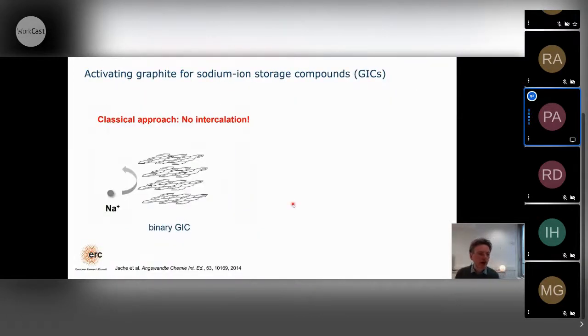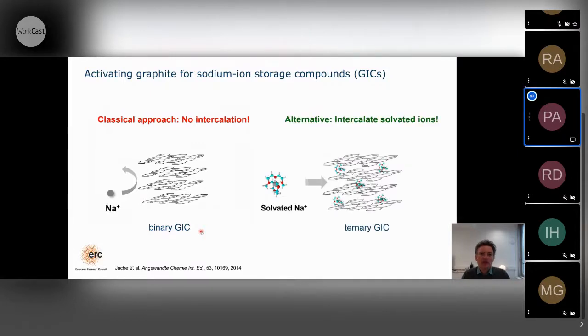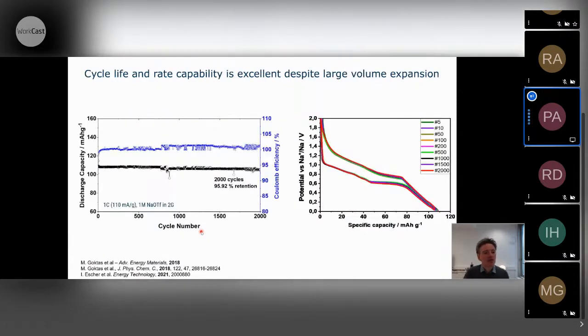From the classical perspective, sodium ions alone hardly intercalate into graphite. So there are no so-called binary graphite intercalation compounds that are rich in sodium. And what we do instead is intercalate solvated ions, so the solvation shell along with the sodium ion. In a lithium-ion battery, you really don't want this because it leads to fast aging. But in the case of sodium, this approach is quite promising because it's highly reversible. So we intercalate not the naked ions; there's no stripping off of the solvation shell during charge transfer. We intercalate the solvated ion, which is of course much larger, but surprisingly works very well. And how well is shown here. These are 2000 cycles, and you can see the capacity is completely constant.